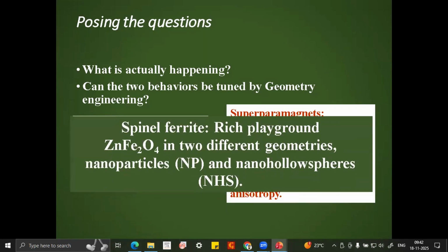With this in hand, we have chosen the spinel ferrite system, which is a rich playground where we can play with cationic disorder, where we can dope in the tetrahedral site or in the octahedral sites. Out of the spinel ferrites, we have chosen zinc ferrite, because of non-magnetic zinc and magnetic iron, so magnetic disorder can also be induced. In the zinc ferrite system, we have chosen two different geometries: one is nanoparticle, another is nanohollowsphere. That I'll come to later.